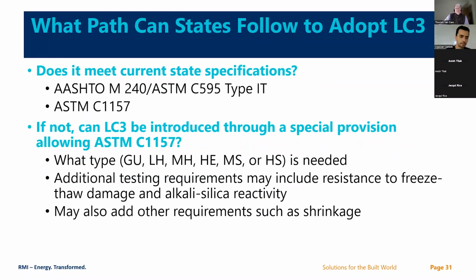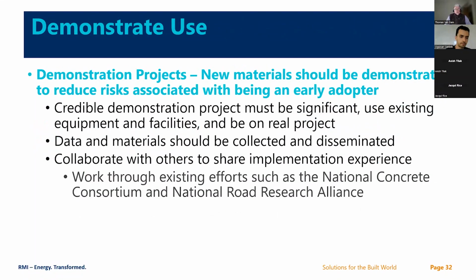So what can a state or an agency do or follow to adopt an LC3? As I mentioned, the first thing to do is look at your current specs, work within them, see if you do allow that ASTM C595 type 1T, and that is one way to work within your current specs. If you don't have this avenue, you really can introduce the LC3 through a special provision, again, either based on the type 1T or an 1157. And then you could throw in some additional testing requirements, and maybe some other requirements like shrinkage and resistivity would be good things to look at. And then develop a specification with partners that you could utilize. Next slide. The bigger question is, how do you utilize it?